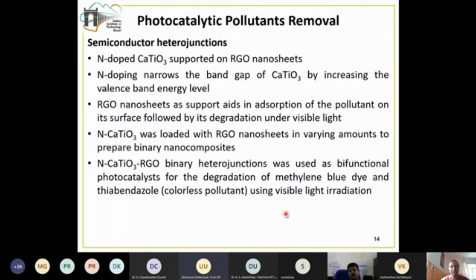This RGO nanosheet plays a dual or multiple role. The main role is acting as a support for the adsorption of the pollutant. Second, it is also helping in the degradation of the pollutant under visible light radiation. In this case we prepared the N-doped calcium titanate in varying amounts with RGO to prepare these binary nanocomposites. These materials were used as bifunctional photocatalysts. Why bifunctional? First, the adsorption process happens and then the degradation happens. So it's a bifunctional photocatalyst for the degradation of a model pollutant.